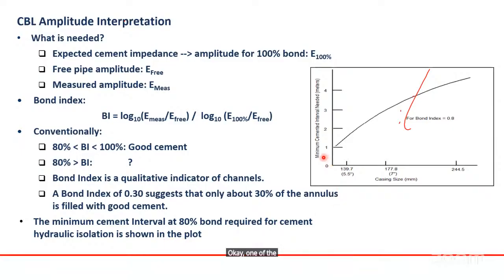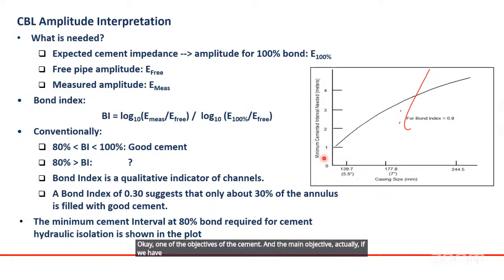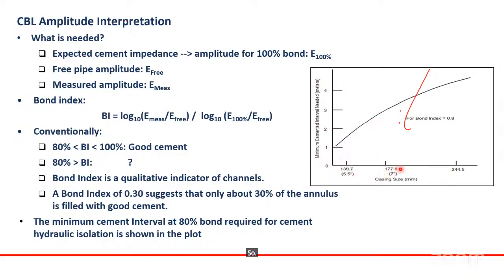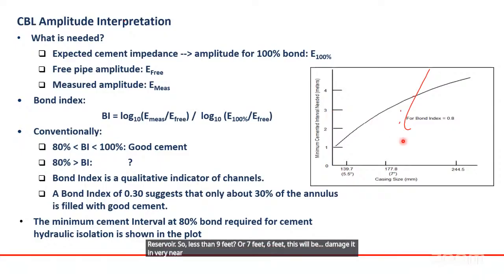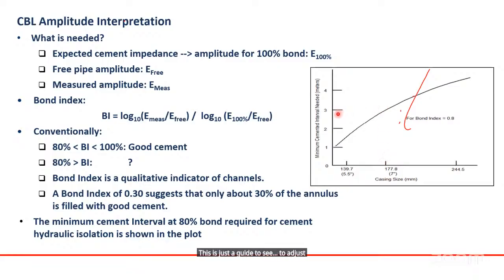One of the objectives of the cement, and the main objective actually, is that if we have two reservoirs, we want to isolate between them. So this chart gives you the minimum cement thickness needed to isolate the reservoir, based on the casing diameter. If you have a 7-inch liner, you need at least 3 meters, about 9 feet of cement thickness, to isolate between both reservoirs. Less than 9 feet, or 7 feet, 6 feet, will be damaged in the very near future. So this is just a guide to tell the drilling team that I need 9 feet of good cement with no channels between the two reservoirs.